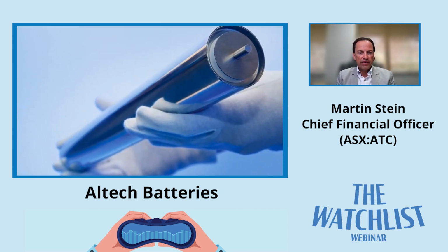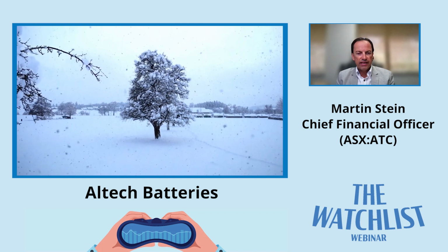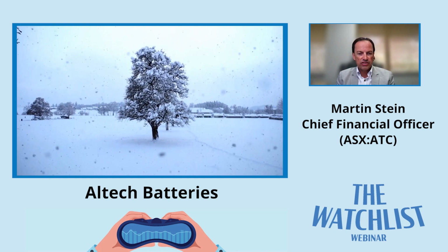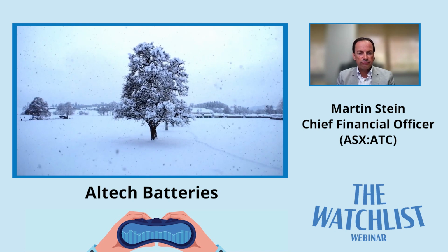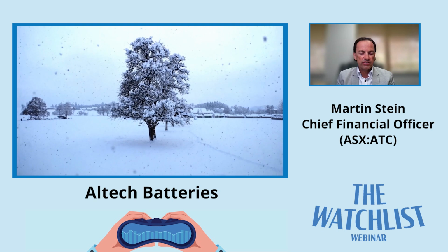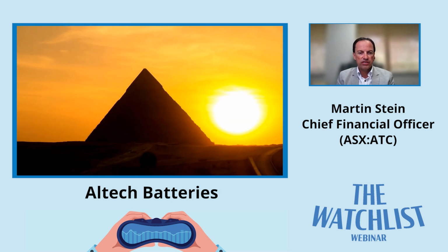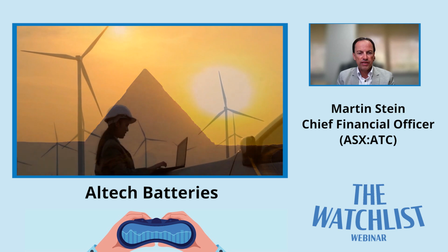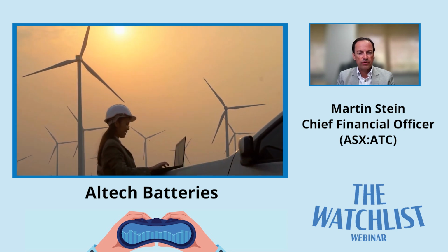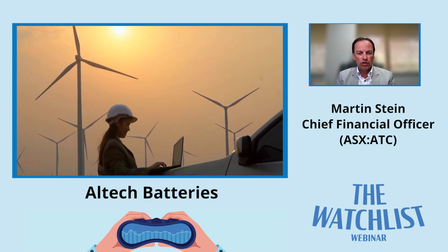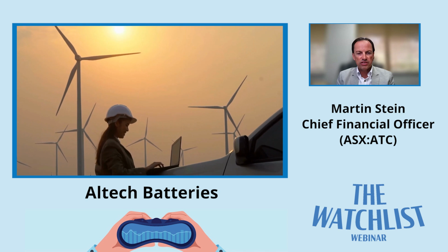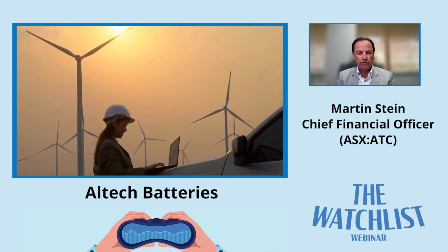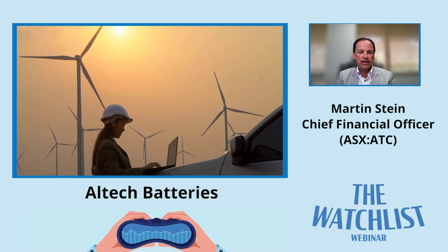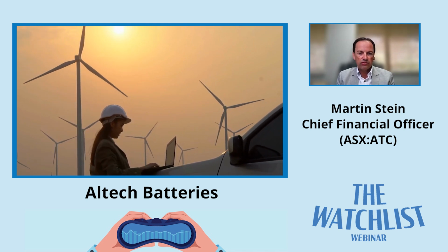Now, the advantages of this battery are that it doesn't have the viscosity issues of lithium. We can take this battery to minus 40 degrees Celsius to positive 60 degrees Celsius, and it doesn't impact on the operation of the battery. It can be used in any geographical region. We also have a long life because the sodium doesn't degrade like lithium. These batteries go for 15 years and the sodium does not degrade.